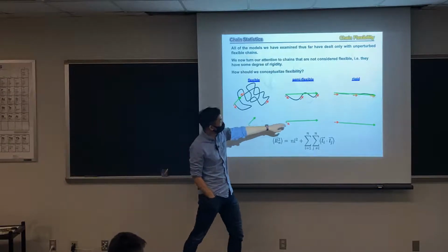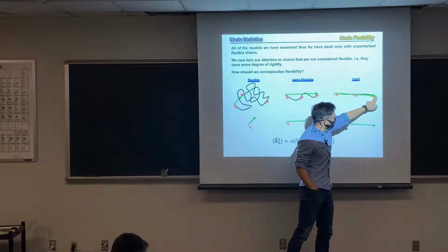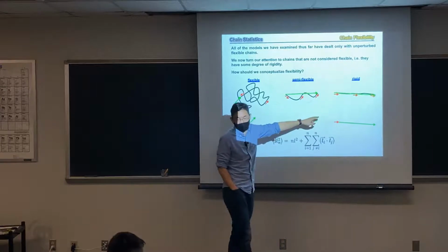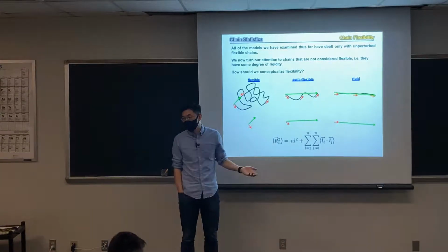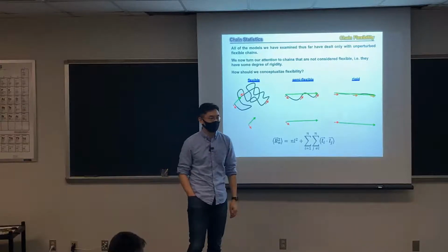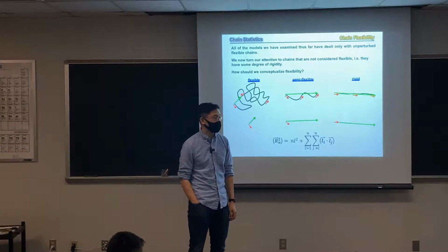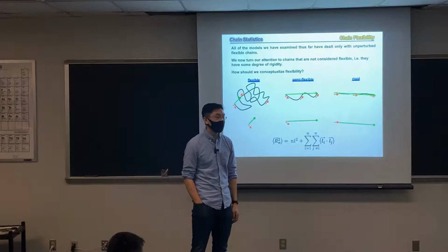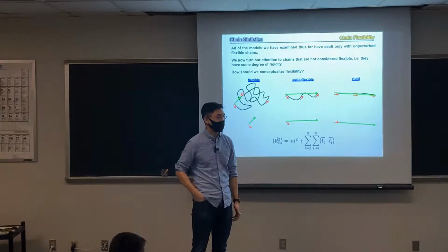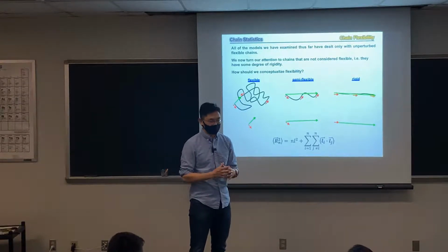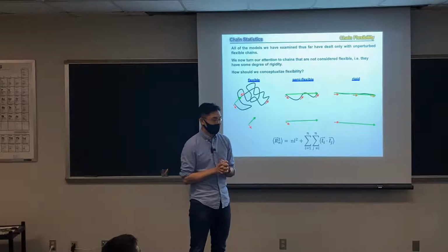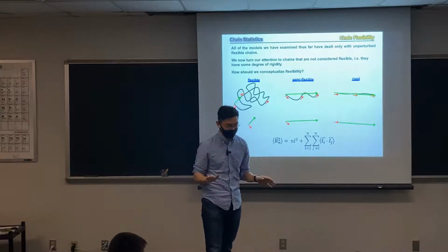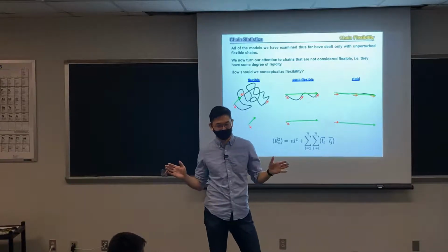And if LC, the contour length, and LP, the persistence length, are on the same order, or even in some cases you might calculate that LP is bigger than LC, theoretically you should consider your polymer like a rigid rod. A piece of stainless steel, but at much smaller length. So it's relevant. It's like philosophy. It's relevant depending on what scale you're talking about.